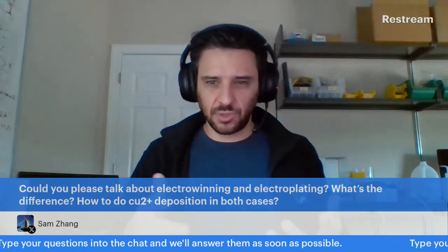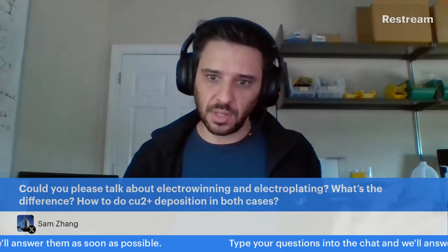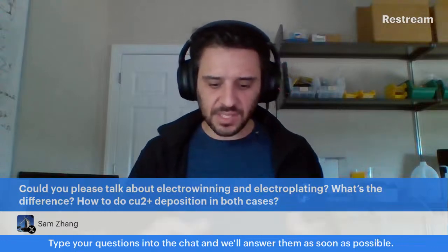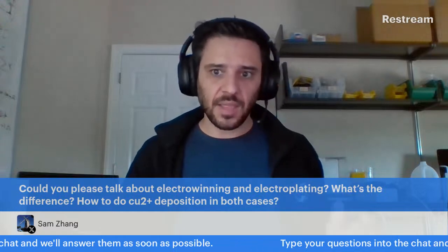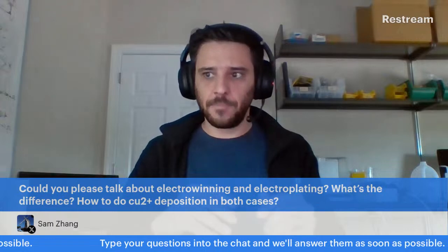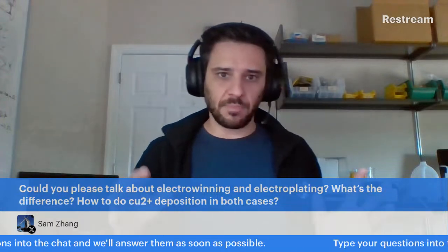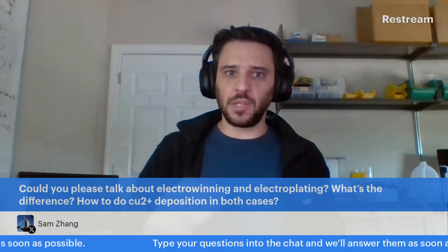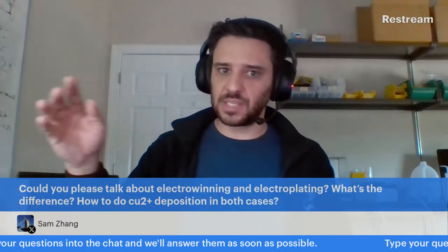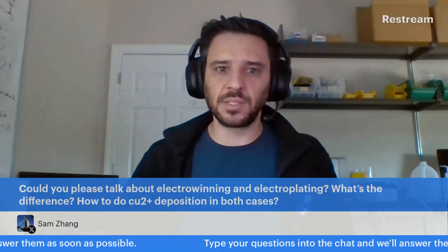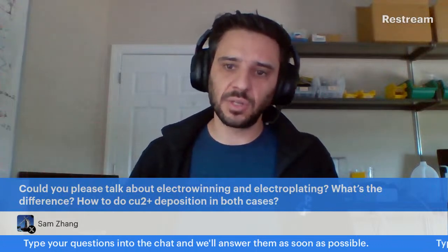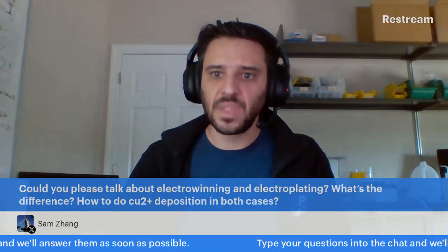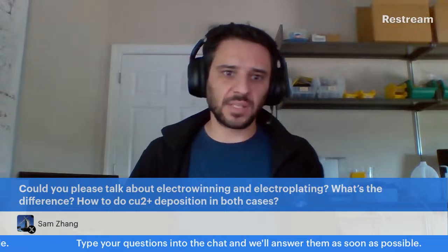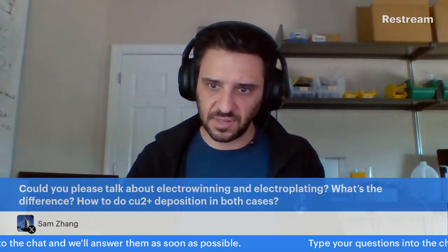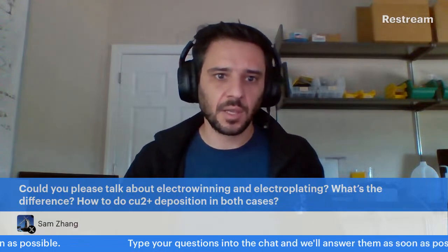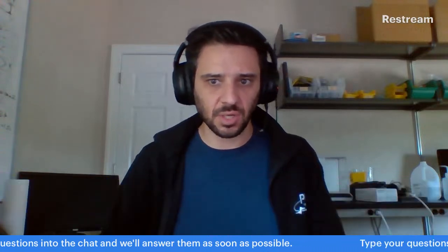On the other hand, in this electrowinning, if I'm understanding it correctly, which is possible I've misunderstood a little bit, in a leaching process or a deposition where there's a lot of other metals present, that isn't always the case, right? Because you could have interference from other deposition. If you have copper, but you have tin and zinc and all these other metals, you're going to need to be careful because the film you form might not be pure copper. It might be an alloy. It might have other metals. It depends on what potential you pick. It probably requires a little more care in the potential that you select, and that would probably impact the film that you get as well. So that's the best that I can describe those processes, without any specific data. I don't have any electrodeposition data in front of me, but hopefully that's a relatively clear, concise explanation of electrodeposition or electroplating.